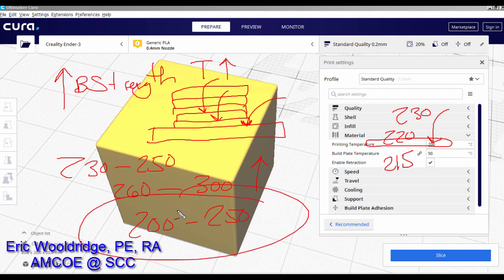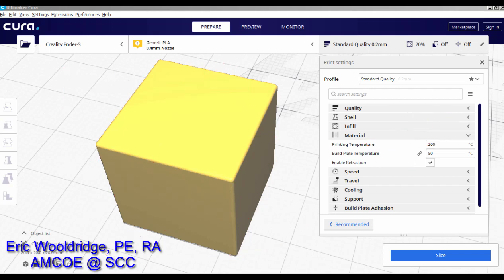Now as far as print time, it doesn't make a whole lot of difference in the trade-off there. You can get too hot, and if you get too hot, then the material doesn't flow too well, and your extrusions can be a little bit stringy. And also what can happen, especially with certain FDM type printers, is if you get it too hot, you will get what we refer to as heat creep. Let me just show you here. So this is your nozzle, and this is where your material is flowing out.